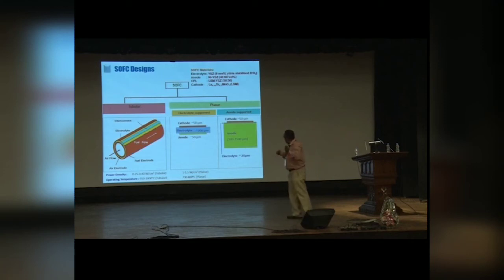So what are the materials? I have another slide, but let me tell you, the electrolyte is basically YSZ, yttria stabilized zirconia, that is 8 mole%. It is commercially available. And the anode we are making by mixing nickel and yttria stabilized zirconia, 40 volume% nickel and 60 volume% yttria stabilized zirconia. Then you have LSM and yttria stabilized zirconia, that is 50-50. LSM is lanthanum strontium manganite. As you can see, this is the perovskite, and this perovskite is used as the cathode, that means this layer, and the anode is basically nickel and yttria stabilized zirconia. And yttria stabilized zirconia alone is the electrolyte. So this is more or less the material structure.